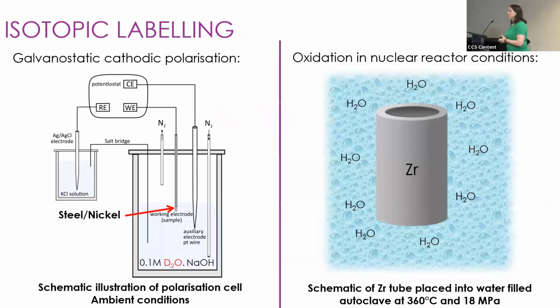So how do we get those isotopes into our metal? We use two different methods depending on what alloy system we're using and the conditions that it would normally experience during service. For our steel and nickel alloys, we did galvanostatic cathodic polarisation. So here we have our sample in a deuterated solution. We're charging with deuterium in this case.